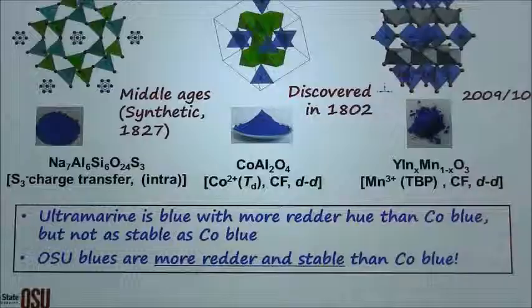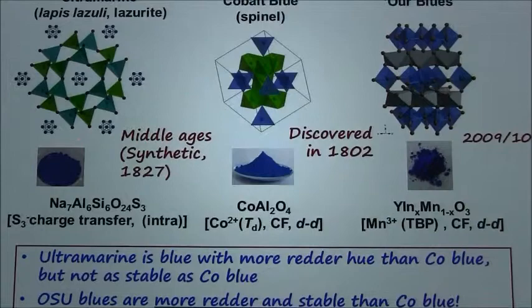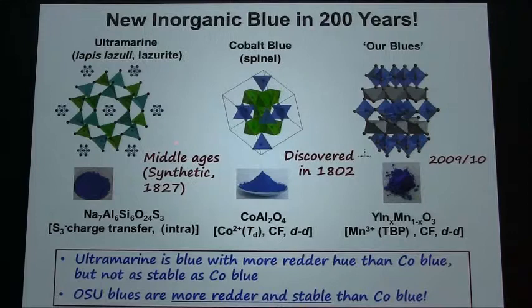This is the blue lapis lazuli. This is the crystal structure of lapis lazuli. There are no transition metals. These are all sulfur clusters, as you can see, that produce the color, because electronic transitions in the sulfur clusters give rise to the blue color. So that was synthetically made in 1827. Then cobalt blue was discovered in 1802, which was the last blue color discovered. And when we discovered the blue based on this crystal structure, in 2009 to 2010, it was after nearly 200 years that a blue pigment was discovered.